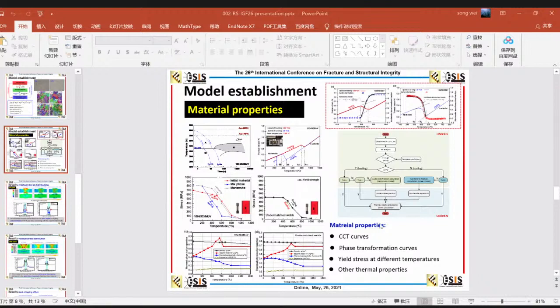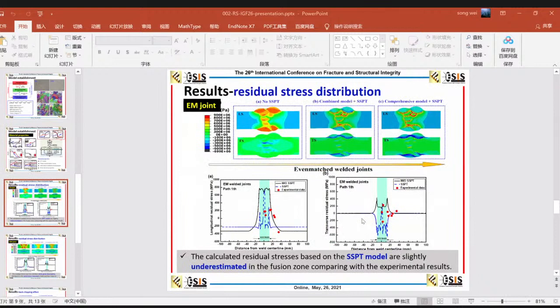Considering the multi-pass processing. So this is the even matched welded joint, from which the result we can see that the calculated residual stress based on the SSPT model is slightly underestimated in the fusion zone compared with the experimental data. Also, we can see in the transverse residual stress direction, the calculated data agree with the experimental data.